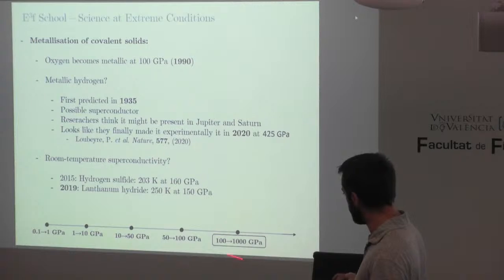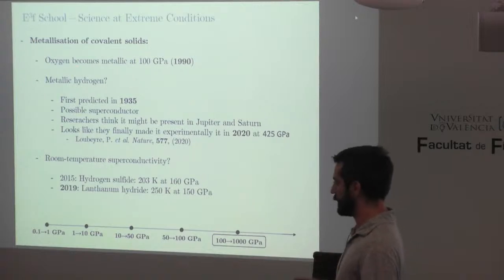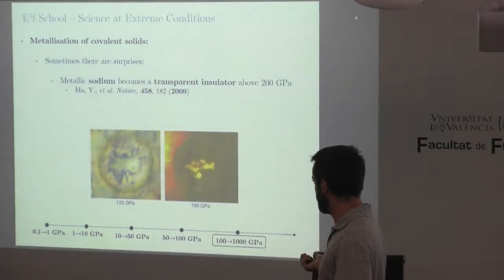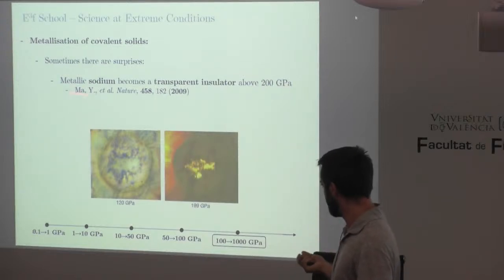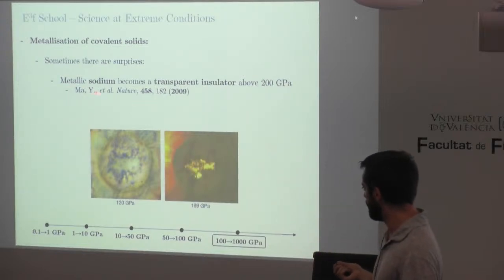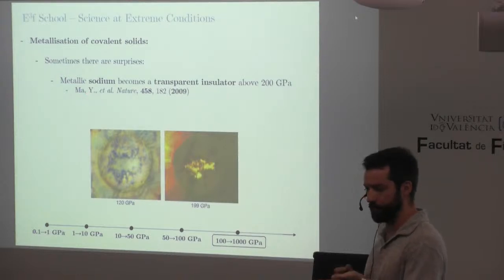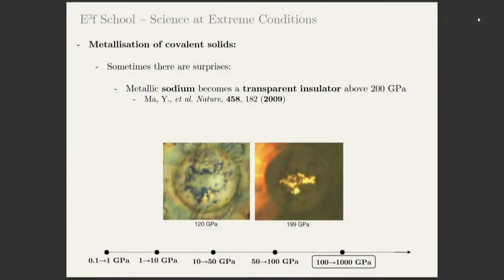I mentioned that at these high pressures, basically all materials become metallic. You never know what you're going to find in science, and this is a nice counterexample. Sodium, which is a metal at ambient pressure, actually becomes a transparent insulator around 200 GPa. In this image here, you can see this here is the sodium metal. It's a shiny silver color at 120 GPa. And then here at 200 GPa, you can see the sample is transparent, and we have yellow light traveling through the sample towards the camera.